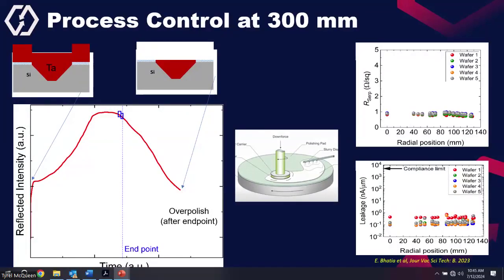And that's how an endpoint algorithm is developed, so that as a function of variations of the pad size and different consumables, your CMP process gives you the same result every time. And here is an example where these 5 wafers were run at different times, but the resistance across a serpentine structure on the wafer remains the same, as well as the leakage across a comb structure remains the same. So now we have established our bottom electrode.